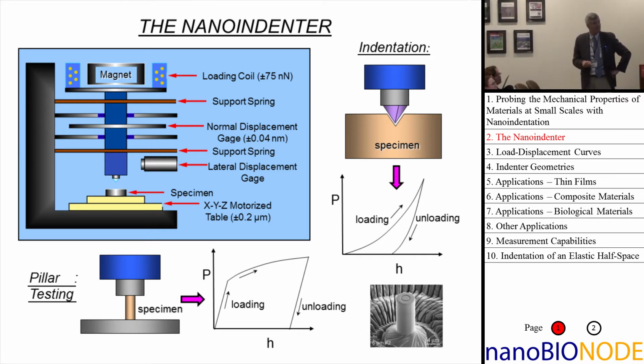I've got another talk tomorrow. We'll talk about these, where instead of using this thing as an indenter, you use it just as a small compression tester. And via things like focused ion beam milling techniques, we can now go in and make small specimens like that. That one's a few microns across. You can make these things hundreds of nanometers across. And you can use this as a compression testing system to measure force and displacement as you would in a macro scale test on a compression specimen to get force displacement data, again, down at the micron and nanoscale.